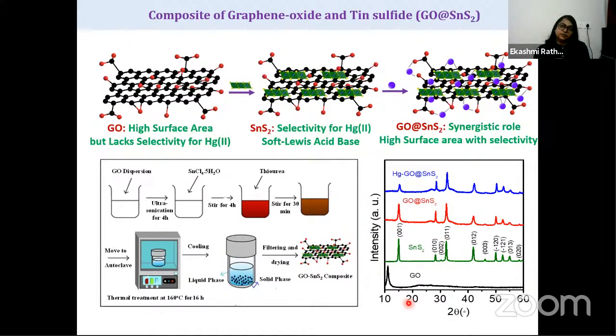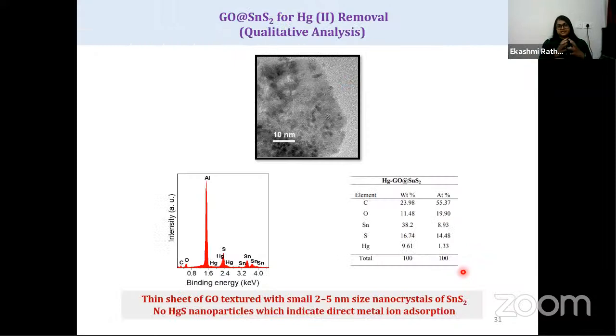Here in the powder X-ray diffraction pattern, you can see the spectrum for graphene oxide, and this is for SnS2. When you mix these two using this method, we see that the graphene oxide starts having the peaks of SnS2. We then analyzed this sample and wanted to look at the morphology, so we used transmission electron microscopy. Here you can see the structures visualized at just 10 nanometers. These are the graphene oxide sheets, and these dots are coming from the SnS2. With the energy dispersive diagram, we could see that mercury is there in the sample, and we found that there is direct metal ion adsorption from this experiment.